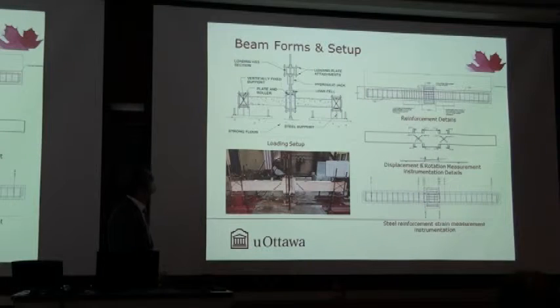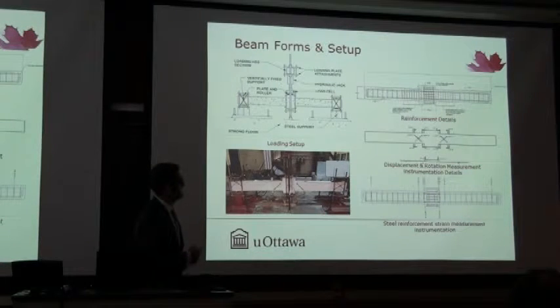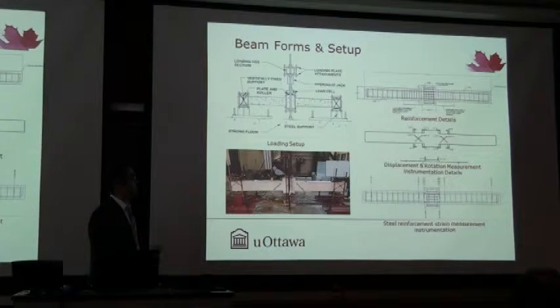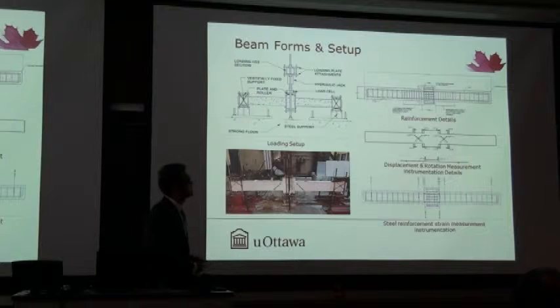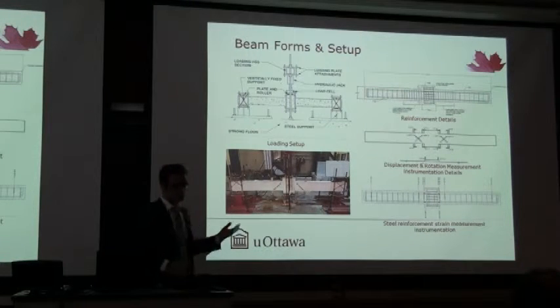This slide shows my loading setup at the top there. We had the hydraulic jack load the beam in reverse cyclic loading, so it was a double valve hydraulic jack. It was fixed, like a hinge at the end, but fixed with respect to vertical displacement. We placed steel strain gauges in the longitudinal steel reinforcement as well as the hoops. We had displacement cable transducers to measure the rotation of the plastic hinge as well as the rotation due to anchorage slip and the shear deformations. We also measured the vertical deformation.